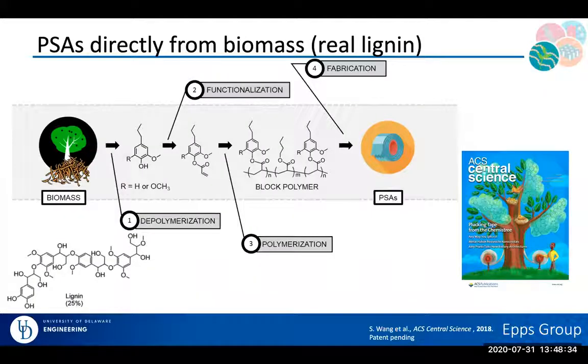Now, those are some things we can do from model or heavily separated lignin. One of the things that we can also do is actually use real biomass and make pressure sensitive adhesives. So in this particular case, we can take biomass. Poplar wood was our example that I'll use for the next several slides. We can take that poplar wood, grind it up in something like a relatively inexpensive coffee burr grinder, depolymerize it using a catalytic depolymerization. In this case, we use ruthenium on carbon. We can get our precursors out, functionalize them to make monomers, make block copolymers, and then fabricate pressure sensitive adhesives and look at their performance.